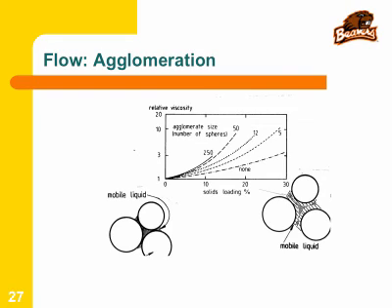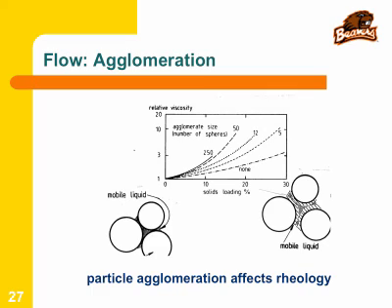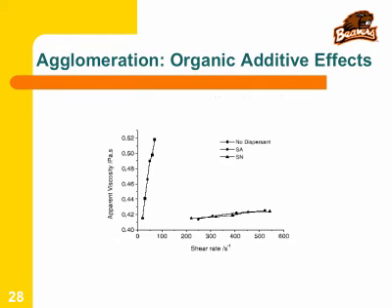So this is immobile liquid over here, right? There's a portion of liquid that does not participate in fluidizing. And so that's the equivalent of increasing the volume fraction. If you increase this, effectively you're having more particles, right, by having agglomerates in a given volume fraction. And so viscosity is going to go up. Right? So agglomeration affects rheology, and for your zirconia particles, what you make with them becomes a major issue if you can't separate them.